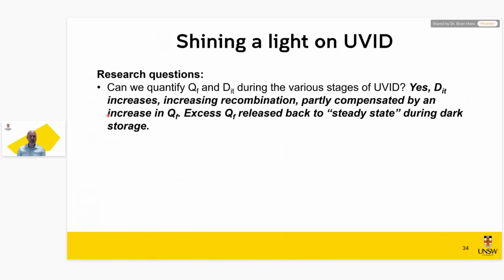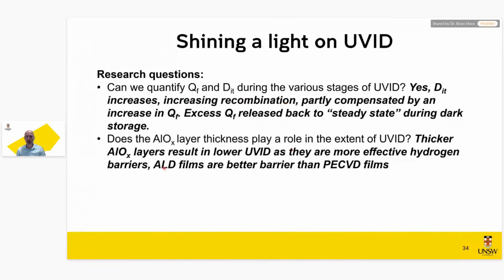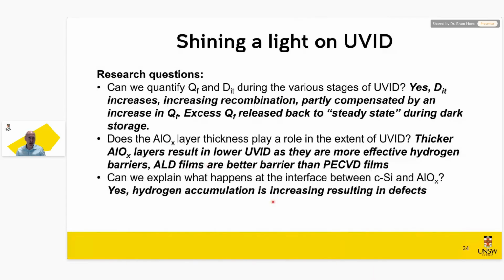So we can answer the research questions we posed. So can we quantify what happens? Yes, and I explained that in the previous slide. Can we do something? Yes, thicker ALOX films work better, and ALD films work better than PECVD. So this is very actionable insight for either you as a solar cell producer or as a buyer to ask for ALD films. And can we explain what happens at the interface? Yes, we believe that it's hydrogen accumulation that is the root cause, and that's why it can be fixed at relatively low temperatures.